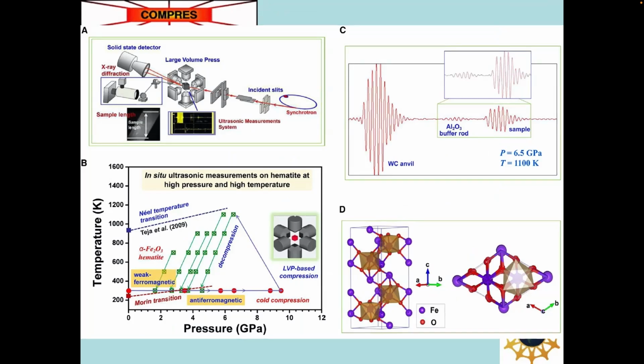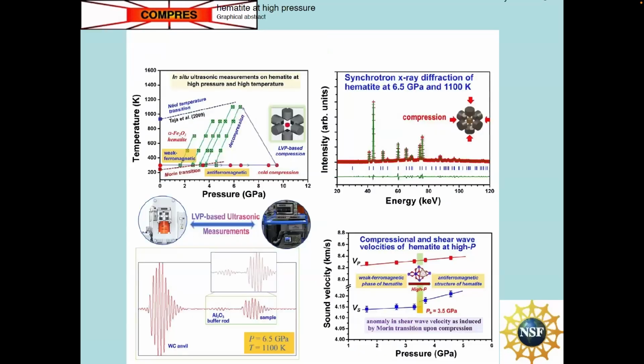Okay. Where was I? I had Anderson's lecture in Czechoslovakia. Then just a few photographs of Ed Schreiber and Orson visiting the diatremes of northeastern Arizona that we did in the 1960s. And then these recent studies of hematite, which are the measurements by Ran Wang in Baosheng's laboratory. Ironically, they used the same specimen that I used with Schreiber back in 1968. The compressional and shear waves versus pressure, and then converting to the bulk modulus and shear modulus.